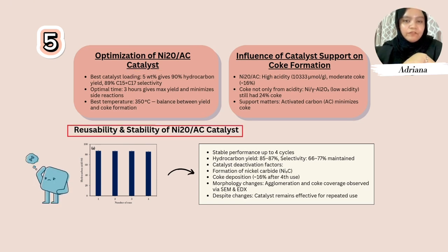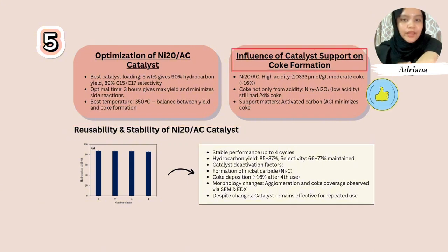The catalyst stayed effective over 4 cycles, maintaining 85 to 87% yield. Slight deactivation occurred due to coke buildup and nickel carbide formation. Activated carbon support helped reduce coke thanks to its mesopore structure. For improved results, nickel can be combined with metals like lanthanum, copper, or iron.